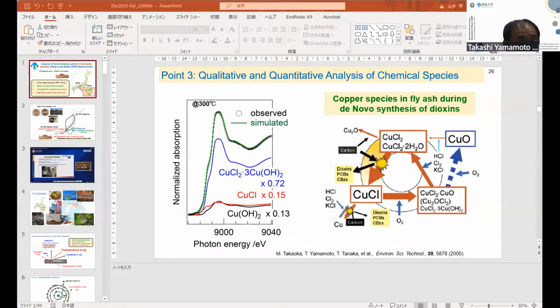Our recorded spectrum is the circle one. By use of the combination, this spectrum can be reproduced using the chloride and hydroxide reference samples. We can know that these samples consist of mixtures of these fractions. Changing the temperatures and the samples, we conclude that dioxins are formed by using the Cu+ species like this.